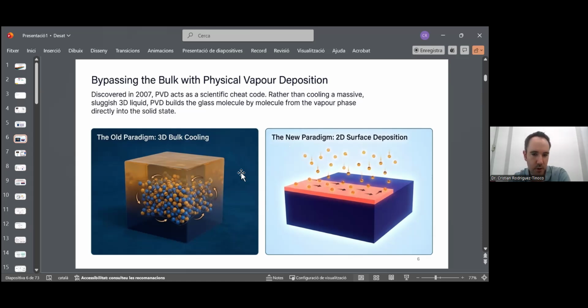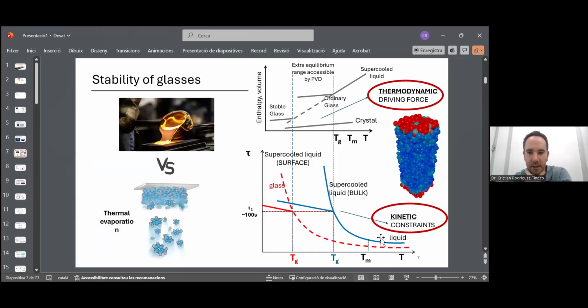So instead of cooling down the whole system and trying to keep the whole system in equilibrium, what we can do is to form this same glass layer by layer by physical vapor deposition. In doing this, if you grow the material layer by layer, the surface molecular layer will have a larger mobility, so it will have the opportunity to equilibrate down to lower temperatures. We can represent this in this way.